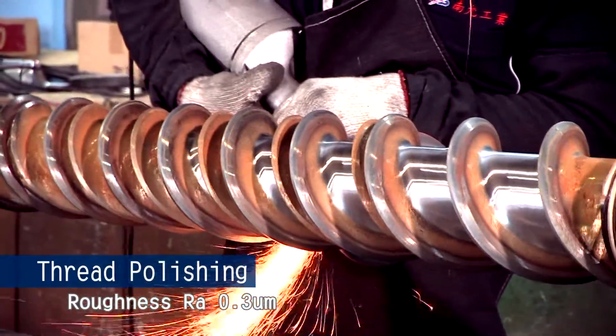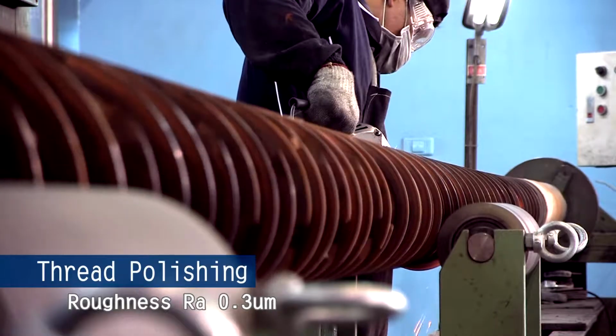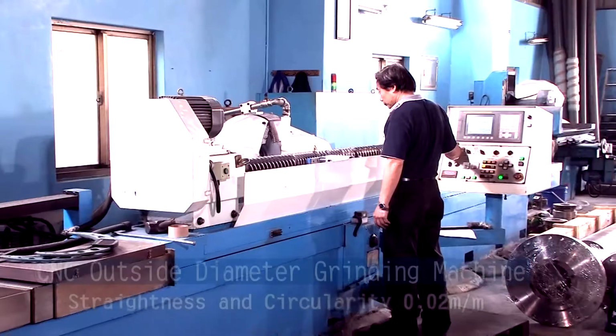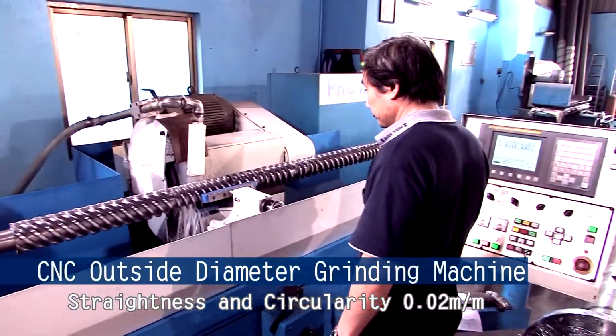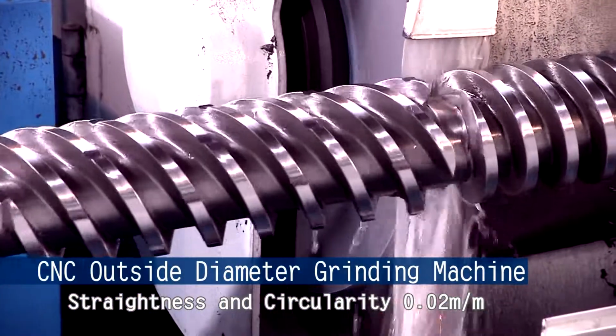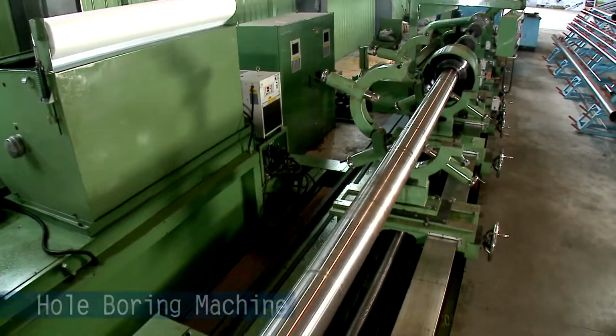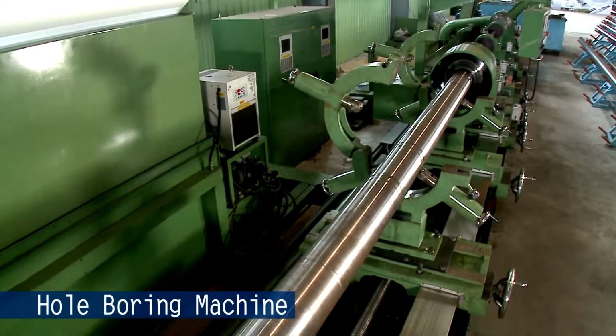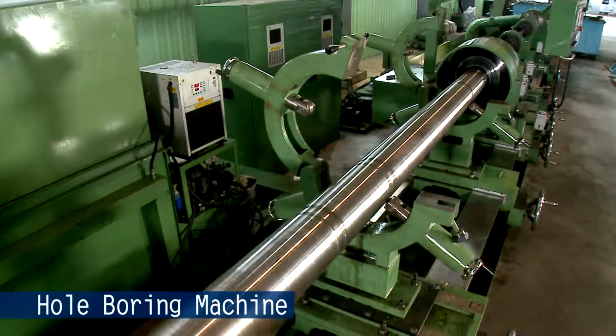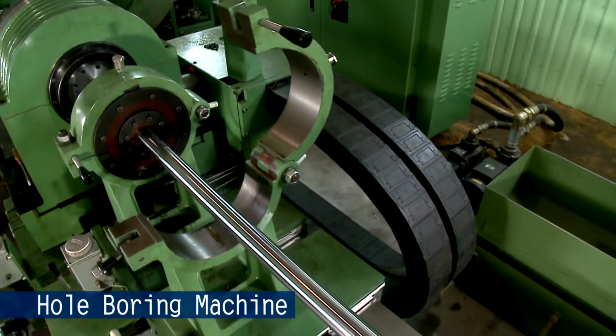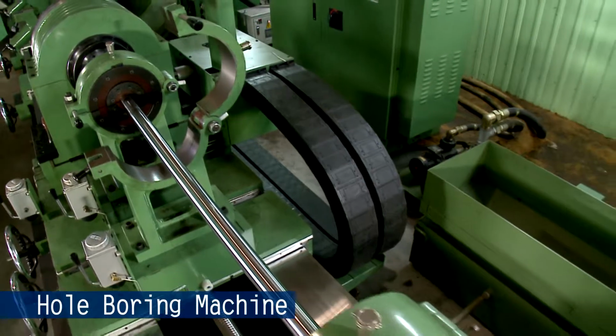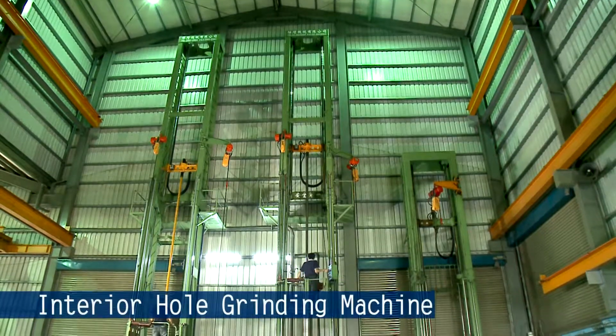Thread polishing. Roughness Ra 0.3 microns. Outer diameter grinding, straightness and roundness can reach 0.02 millimeters. The boring integrated with the barrel enables straight and precise processing angle. Even thickness of bore diameter effectively enhances the feeding smoothness of the screw.